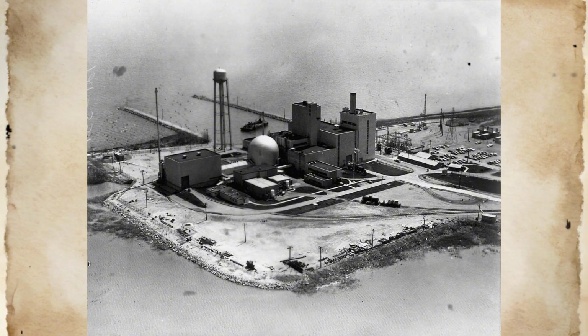Metallic uranium has a relatively low melting point of approximately 1,132 degrees, compared to over 2,800 degrees for uranium dioxide, and it undergoes significant thermal expansion and metallurgical changes at temperatures well below its melting point. These characteristics provided excellent neutron economy and heat transfer properties under normal operating conditions, but they also meant that the fuel had limited tolerance for thermal excursions caused by cooling system malfunctions.